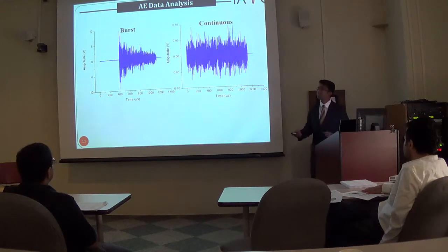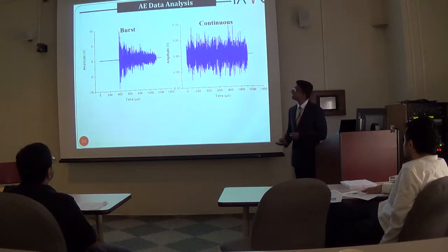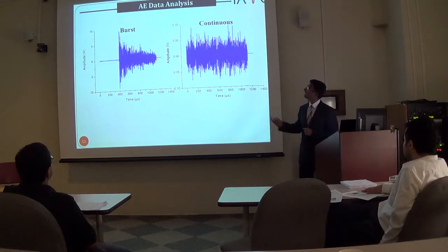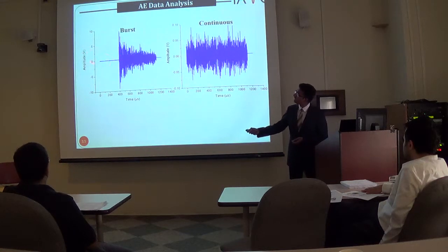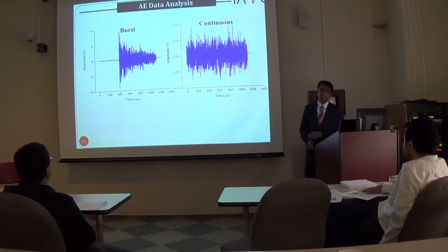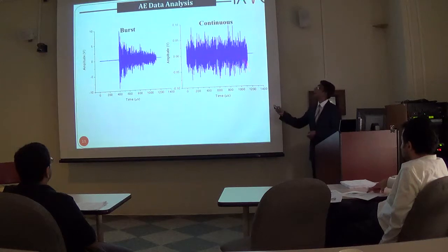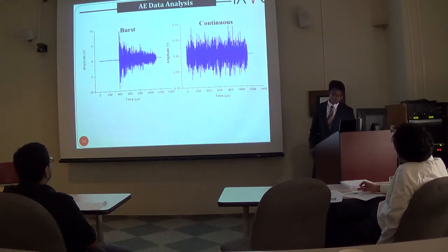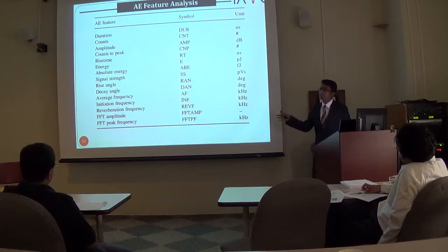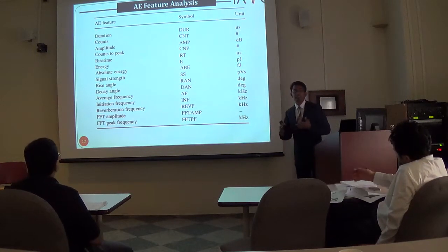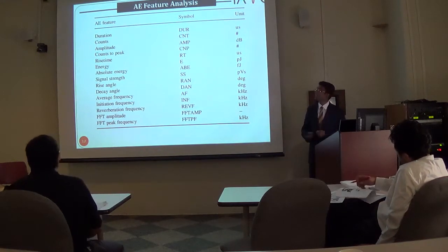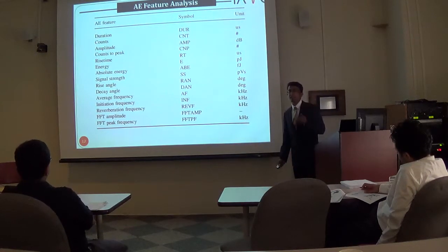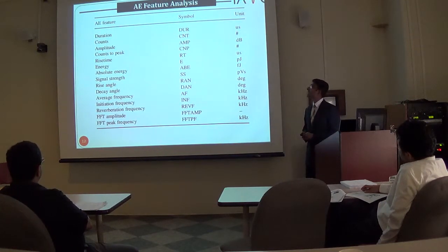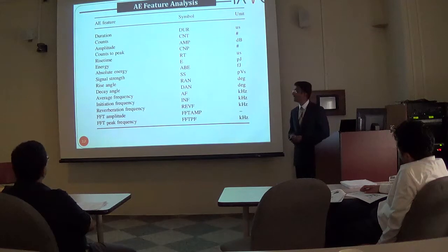Now, the commonly extracted AE waveforms during the testing fall into two basic categories. One is the burst type emission, and the other is the continuous type emission. The burst type emissions have a signature as shown here, with very little activity in the pre-trigger, while the continuous acoustic emission have an AE signature as shown here. Based on these extracted AE waveforms, several AE features are extracted using signal processing techniques, and these are some of the commonly used AE features that are cited for different AE analysis.